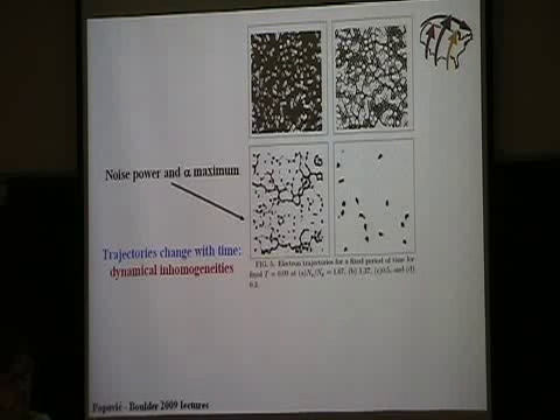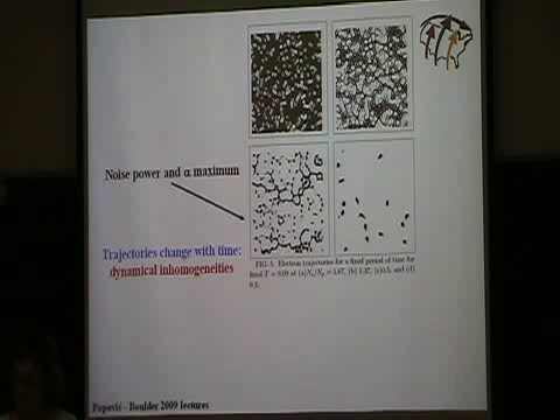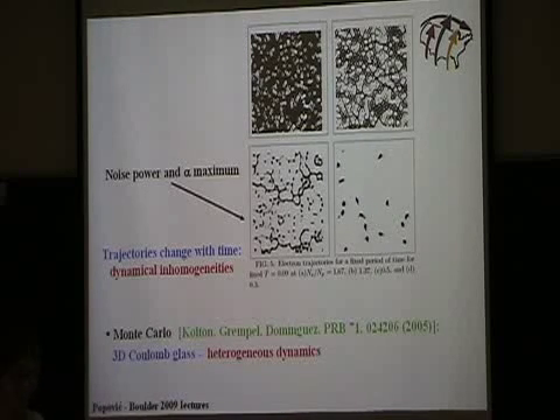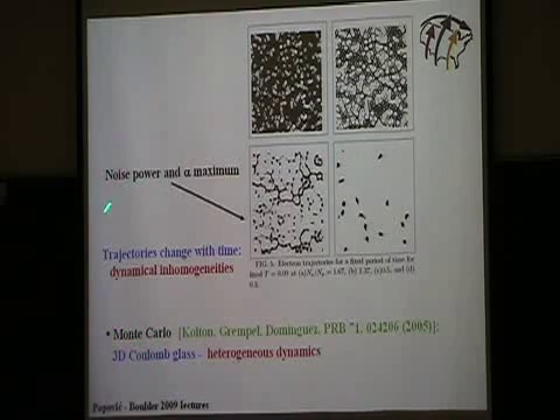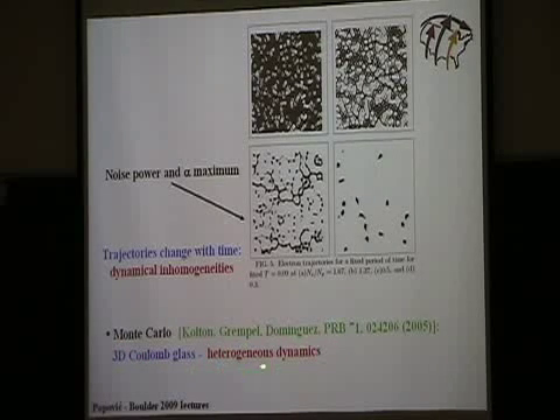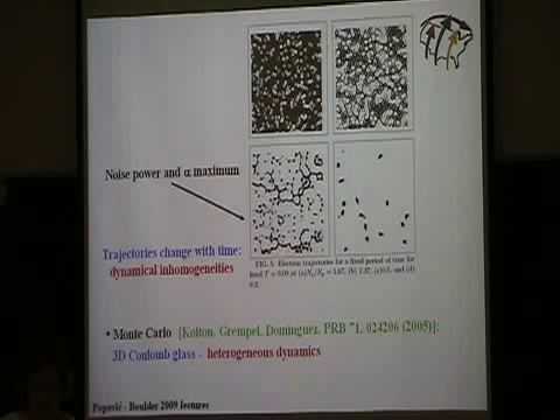So they find evidence for these dynamical inhomogeneities, which is what people have found in many other kinds of glassy systems. Now, in addition to this, it's probably a little bit of a digression, but how on earth do you measure something like that? Well, we measured noise. We measured fluctuations of conductivity, and this shows the electron trajectories. I don't know how they get these pictures from molecular dynamic simulations. I think there are some equations that tell you how they move. Right. So anyway, there is also another kind of simulation, Monte Carlo, which I understand is different from this. And they also find, for a 3D Coulomb glass, a similar kind of heterogeneous dynamics. They find that some electrons move more or less freely through some kind of chain-like path. Others get stuck. As a function of time, some paths shut off, the others open up. So this is all consistent with that. This is all that I'm aware of.